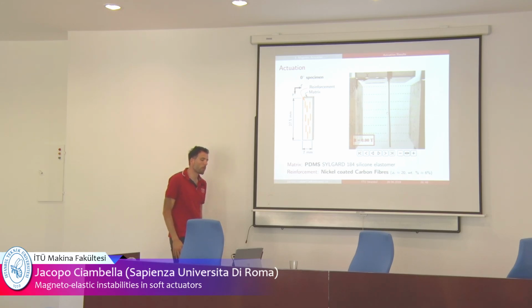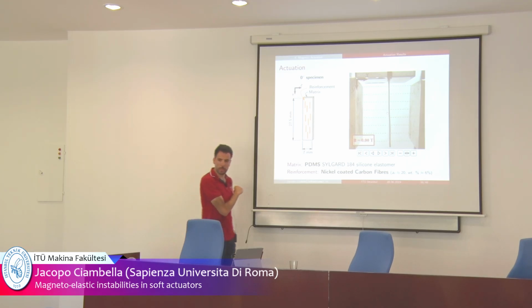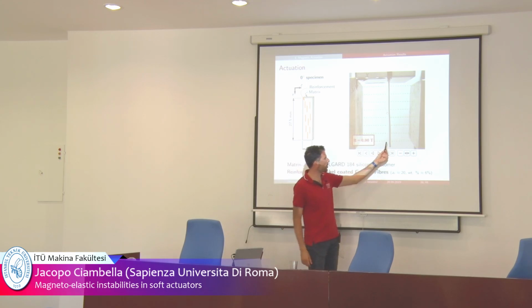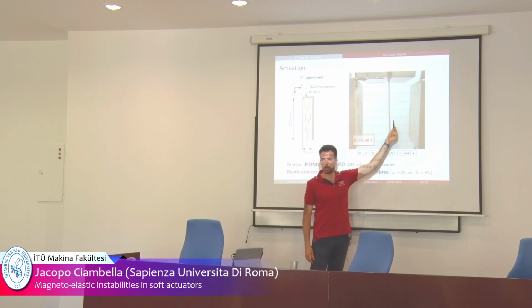And so why is this happening? Now I want to try to explain this effect, which was kind of unexpected. So I'll show you some experiments. Okay, as I said, this is our specimen. These are the plates of an electromagnet. Okay, the field is uniform, and these are the field lines. In this case, the fibers were oriented at 0 degree, meaning along the specimen length, in this direction.